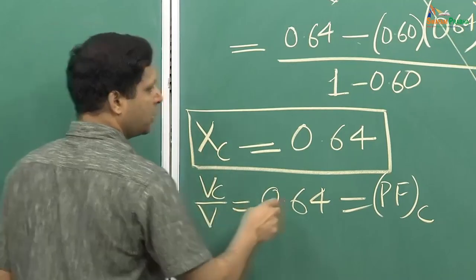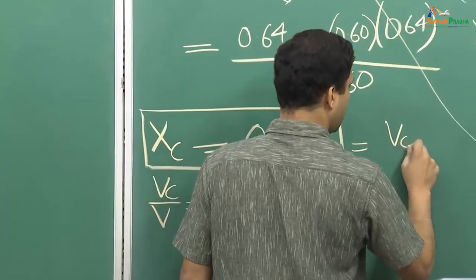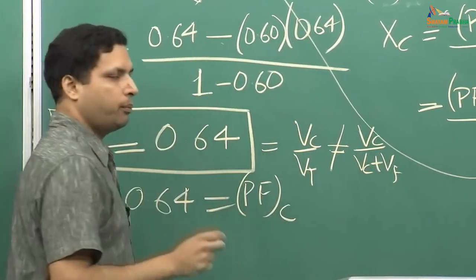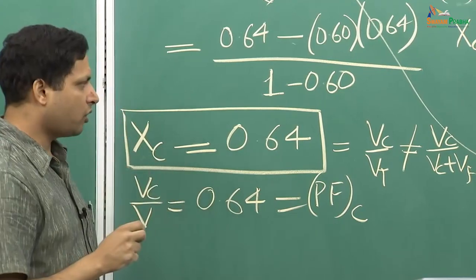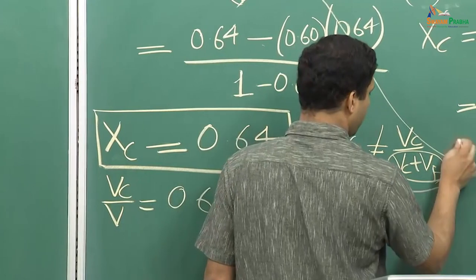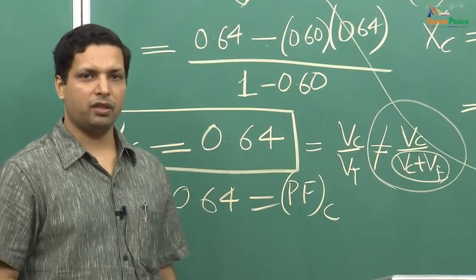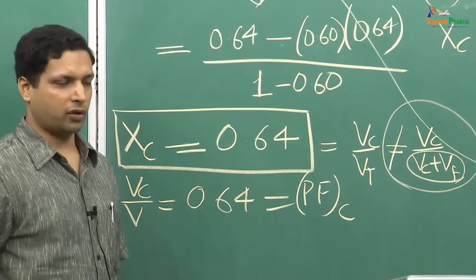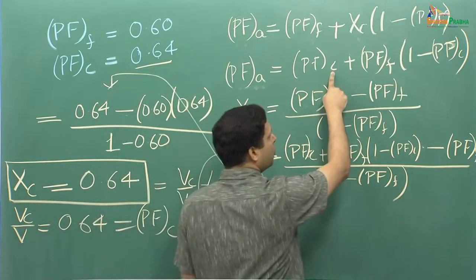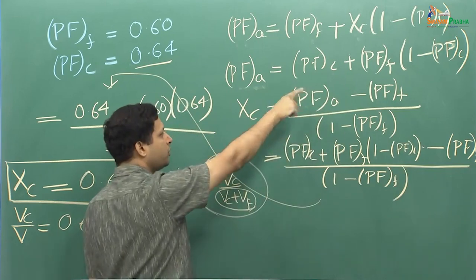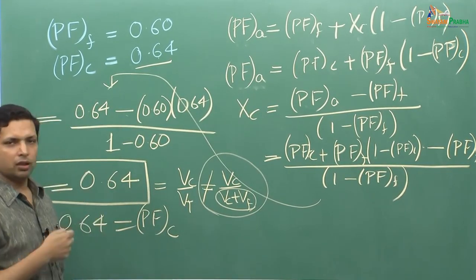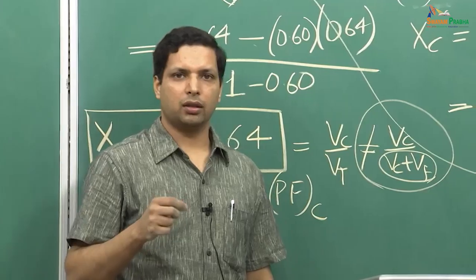One important thing: Xc equals Vc by Vt, but it is not equal to Vc by (Vc plus Vf). So if you wanted to place this on the X-axis from the plot drawn in the last lecture, you will have to find Vc plus Vf, or in other words find Vf. That is an exercise I leave for you — find what will be the value of Vc by (Vc plus Vf) at the point where you get maximum packing fraction. The maximum packing fraction itself will not be difficult; if you put those numbers in you will see it comes close to 0.74, showing the benefit of bimodal grain size distribution.